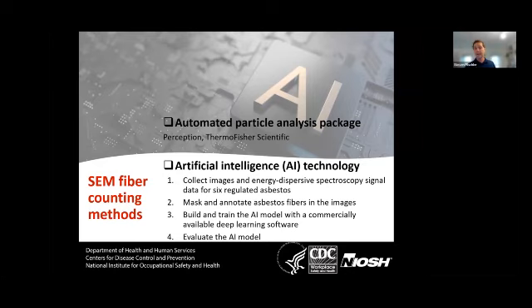And again, if we're only collecting fibers that are of a certain width, or we're able to size segregate that at the collection stage, then the analysis should be easier, and there'd be less confusion with the electron microscopy. And this is the work we're doing currently. We capture these fibers on a filter, and we're comparing the information that we get from the scanning electron microscope, using AI technology, with the information we collect just using phase contrast microscopy, or having actually a person count each of those fibers. So that's really the work we're doing with this new occupational sampler.